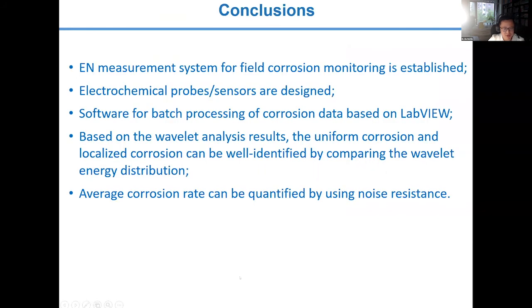Okay, so I'm going to present my conclusion now. We established a noise measurement system for field corrosion monitoring, and we designed electrochemical probes and sensors and software for batch processing corrosion data based on LabVIEW. Based on the wavelet analysis results, uniform corrosion and localized corrosion can be well identified by comparing the wavelet energy distribution. And the last point is that the average corrosion rate can be quantified by using noise resistance.